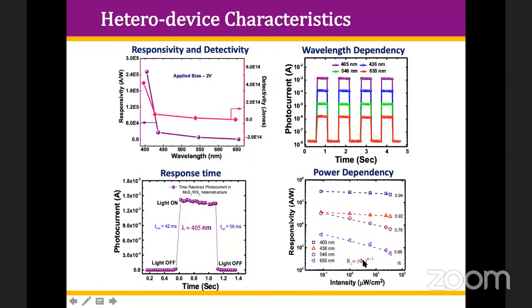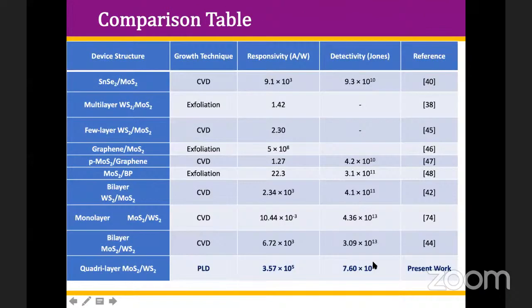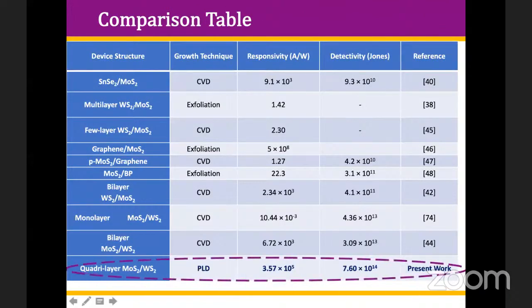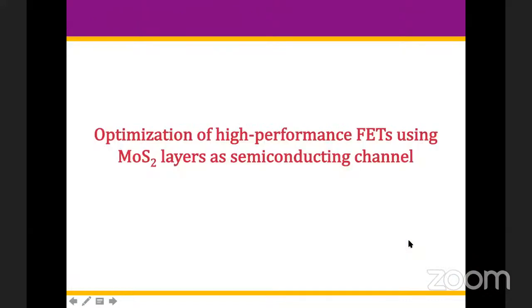And this is the power dependency or intensity dependency of this. And this is a comparison with the literature. You can see the responsivity and detectivity which we found are much, much better as compared to the other heterostructures of 2D material reported in the literature using other techniques. So in this one, the response is much, much better.